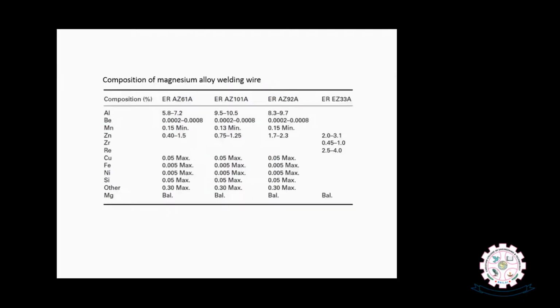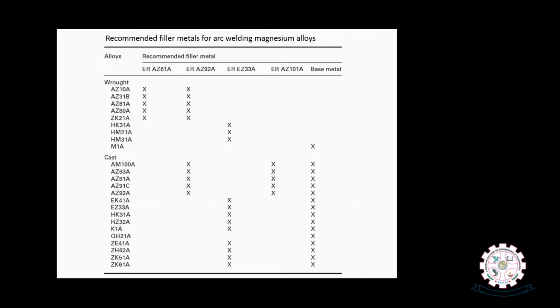And this is the available composition of the magnesium alloy welding wires, and you can observe here aluminum is the major fraction of the alloying element among all the available welding wires, and you can see the distribution of the chemical composition in different welding wires. And what kind of alloy is welded by what kind of suitable welding wire you can get from this table. And here you can compare, depending on the chemical composition of the constituting alloy, the appropriate magnesium alloy wire is selected to complete the fusion welding process.